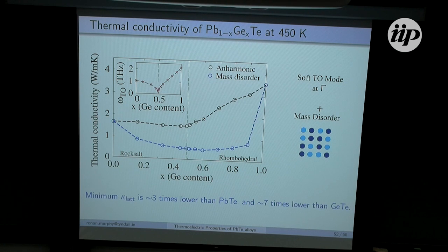So just to mention as well, if we take this minimum value and compare it to lead telluride, we see that the thermal conductivity is reduced by about a factor of 3. And then comparing it to germanium telluride, we see that it's reduced by about a factor of 7.